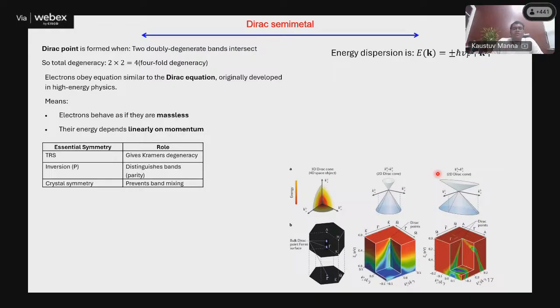So what is the condition you have to satisfy so that you can have such a protected band crossing, like a linear band crossing, in the bulk of the material? Because the linear band crossing carries huge importance, as I explained. Linear band crossing means massless particles. Massless particles mean the mobility will be huge, and the MR effect will also be huge. So it has vast potential from an application point of view. That is why the Dirac semimetal is another stage of complexity added to the topological insulator.